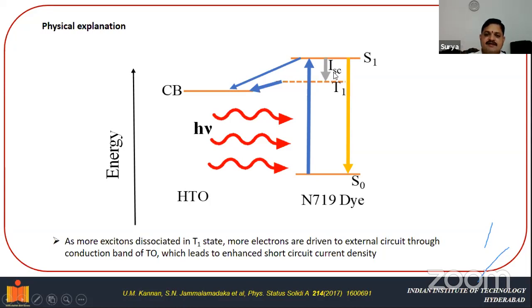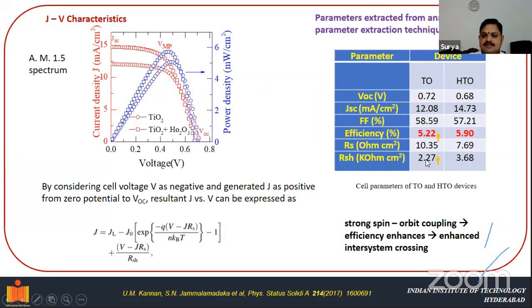Because of the addition of the holmium oxide to our device, the transition between the singlet excited state and the triplet excited state is unlocked, which leads to the enhancement in the efficiency of the device. As more excitons dissociate in the T1 triplet state, more electrons are driven to the external circuit through the conduction band of titanium dioxide, which leads to enhanced short circuit current density. As you can see here, the short circuit current density is also enhanced when we add the holmium to the device.